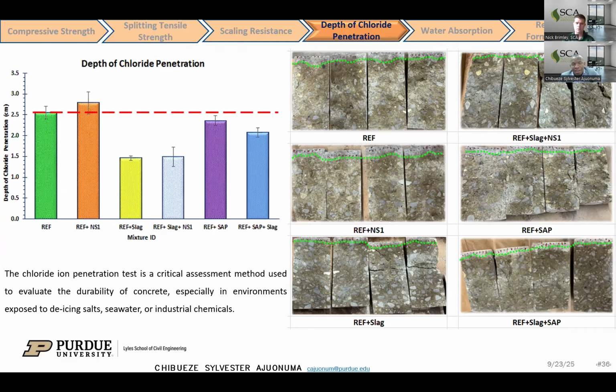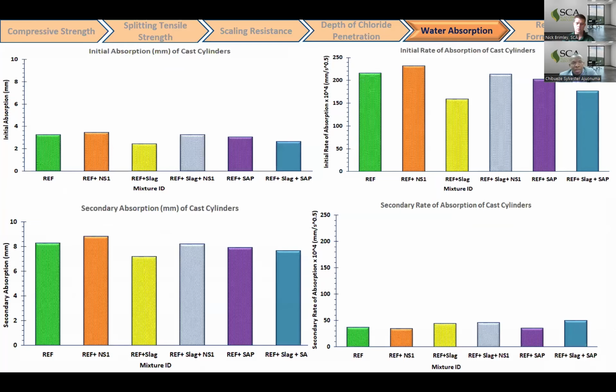And then also, if we check the mix with SAP, there was also a reduction in the depth of chloride ion penetration. And we also evaluated the water absorption. The same trend that happened in the depth of chloride penetration was also evident in the rate of water absorption. The addition of slag helped to reduce the water absorption. This can be beneficial, as it will help to reduce the ingress of water and substances that can be detrimental to the concrete.